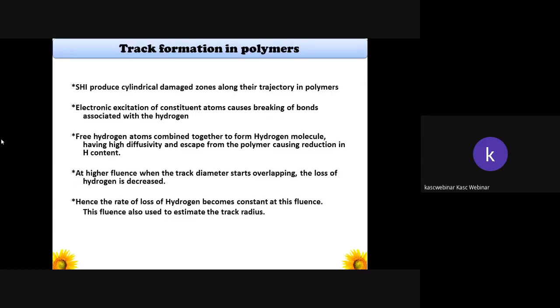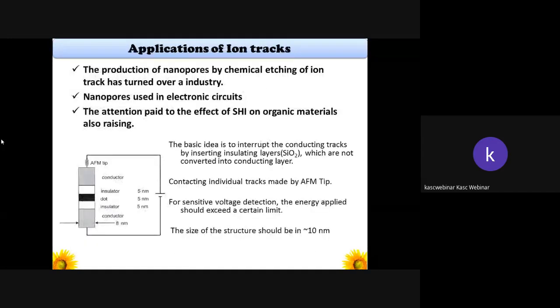And how are we going to utilize this columnar track? Especially, the production of nanopores by chemical etching of ion tracks has turned into an industry. These nanopores are used in electronic circuits. The attention paid to the effect of swift heavy ions on organic materials is also rising. Actually, the basic idea is to interrupt the conducting tracks by inserting certain insulation layers like silicon oxide, which are not converted into a conducting layer, and then contacting individual tracks made by AFM tips. For sensitive voltage detection, the energy applied should exceed a certain limit, and the size of the structure should be approximately 10 nanometers.